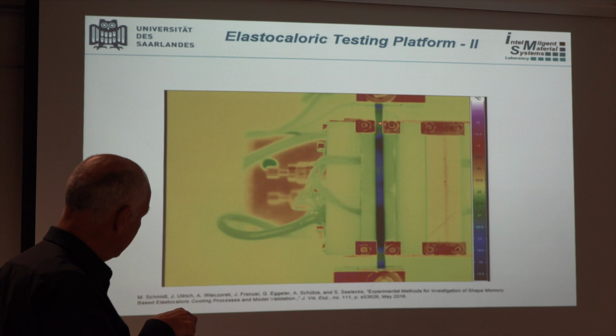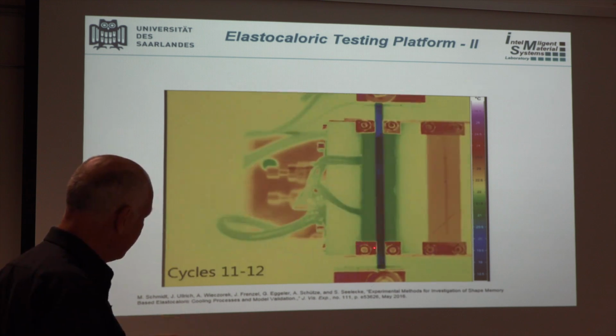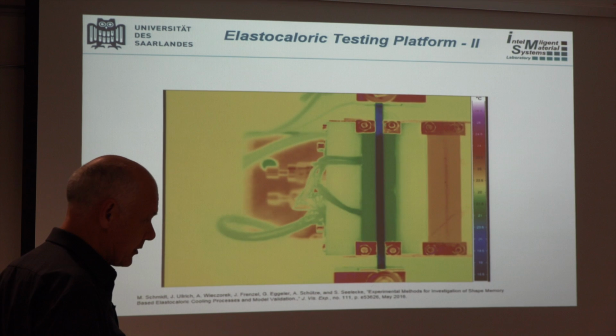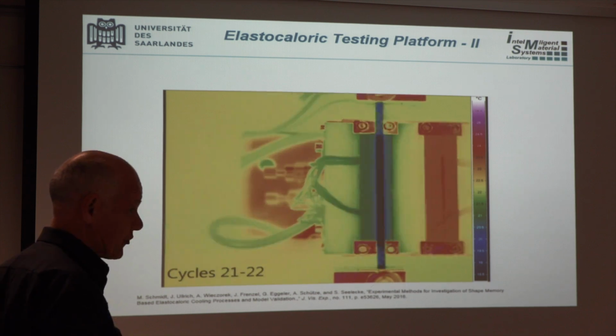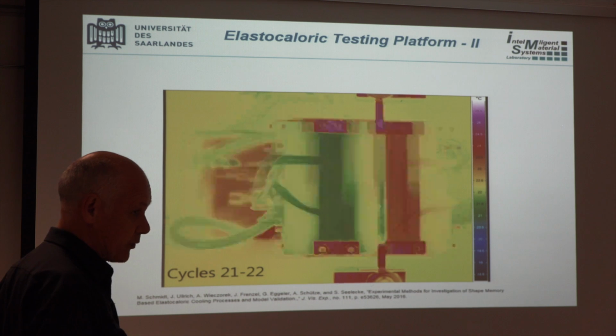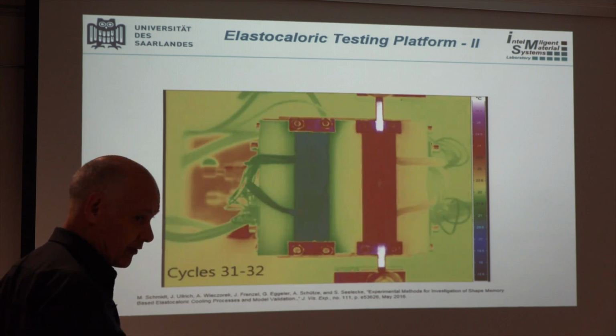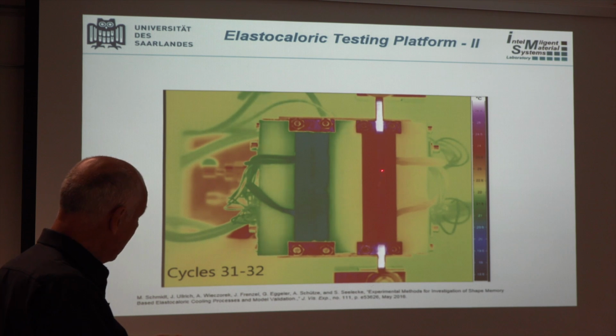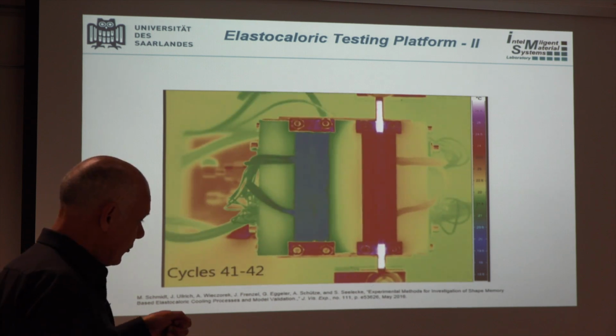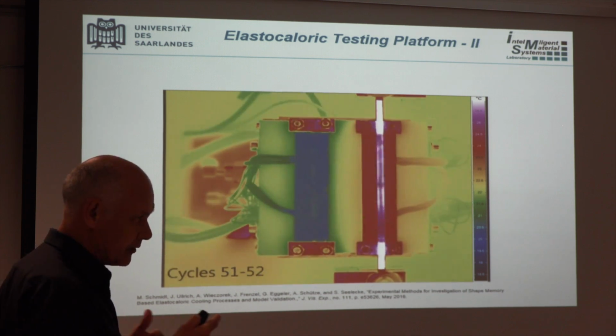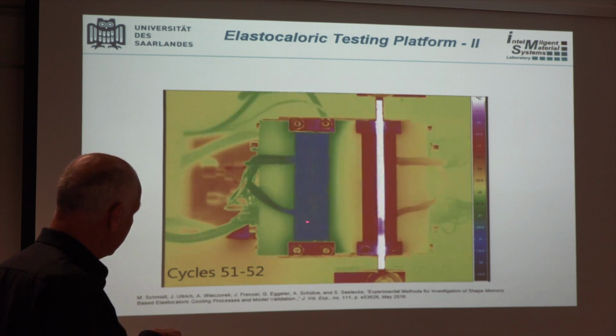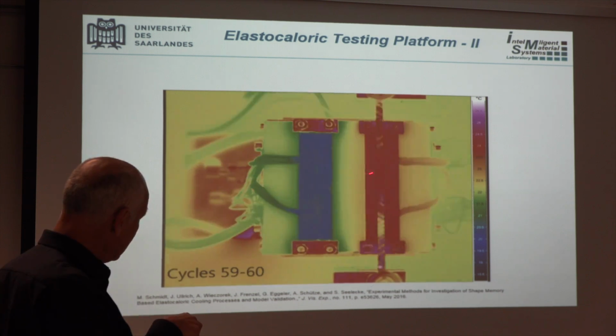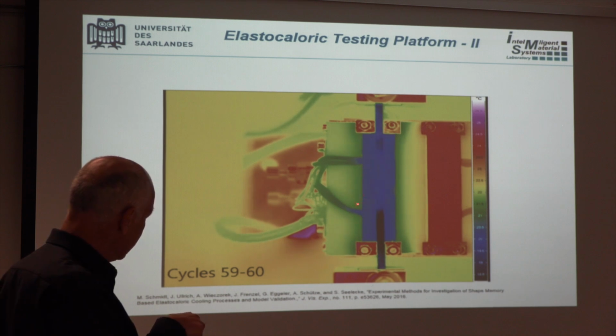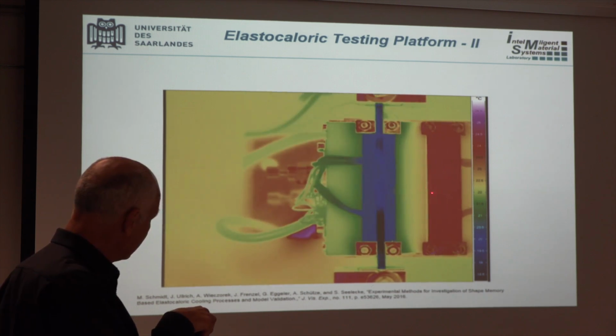Here you see stretch, unload, you see how immediately upon stretching this thing heats up quite a large temperature span. So you can achieve about 20 Kelvin with respect to ambient by just stretching this wire. And then you let it cool on the heat sink, and when you restore, it drops another 20 below ambient, so that you have a temperature span of maximally 40 degrees that you can bridge with these materials. And you can nicely see how the cold shape memory alloy extracts heat from the heat source and transports it over to the heat sink. And after a number of cycles,